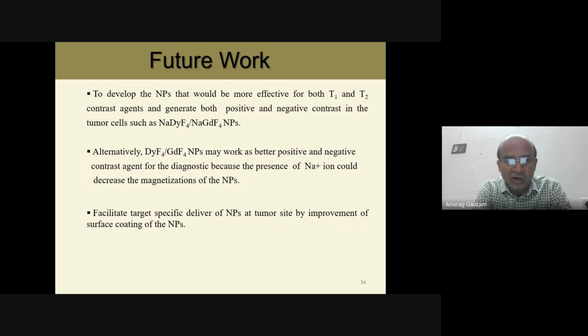If we coat this nanoparticle with PEG, polyethylene glycol is the one that evades the RES system. So we can coat with that, or we can use these particles as dysprosium fluoride or gadolinium fluoride for both diagnosis. And this can be used to facilitate target-specific delivery of nanoparticles. We can still use antibody and surface coating, all can be done.